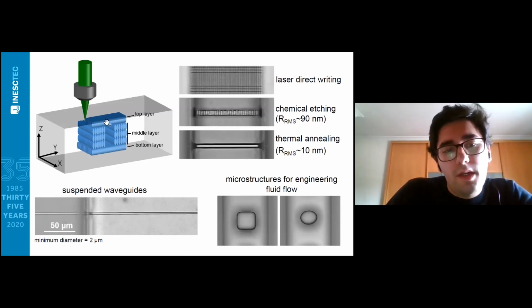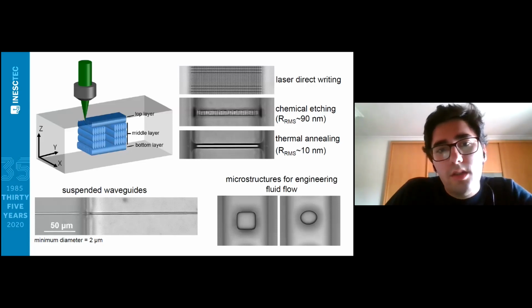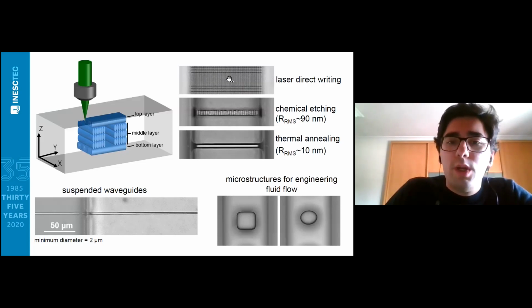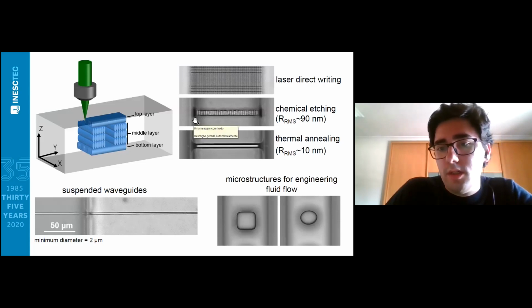For instance, here, if I leave a small silica core unirradiated, so as you see in this picture, there is a gap that we left unexposed. When we do etching, we will end up with a silica core suspended, attached to both sidewalls of the microfluidic channel.